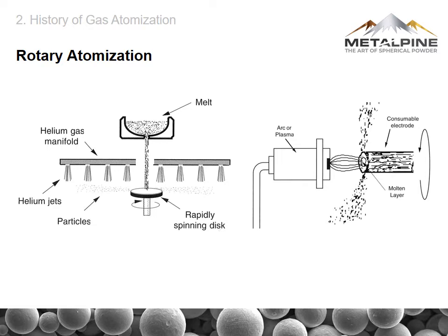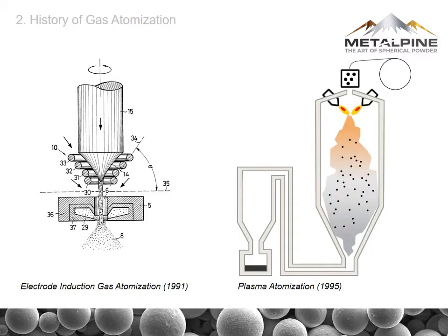On the right side you see the plasma rotating electrode atomizer. It's a consumable electrode that's heavily rotating, and the plasma or arc is applied on the face of this electrode, melting the metal on the tip, and due to the rotating speeds, the melt is also divided into fine particles at the edge of the electrode. Also here, for some applications, a drawback is that not really ultrafine particles are formed with this method. Those two atomization systems are still commonly in use.